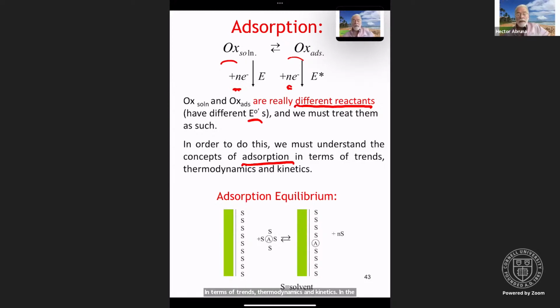In the simplest of cases, we can think of adsorption equilibrium as shown in this profile here. The green is the electrode surface, S stands for solvent, and so we have an electrode coated with a layer of solvent. We have a species in solution that's solvated, and if that species adsorbs, it becomes in intimate contact with the electrode. There's an inherent interaction in there. In so doing, it liberates n moles of solvent. It displaces some solvent from the surface. If we assume that the solvation here is 4 molecules, in the process of adsorbing, this n would be 5, because you have 4 from these and 1 from the surface.